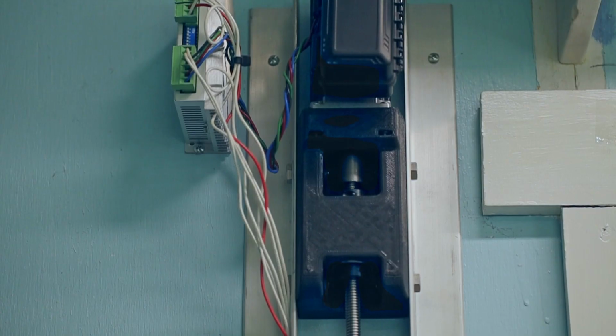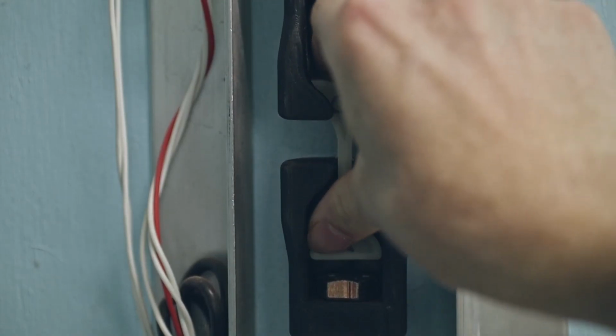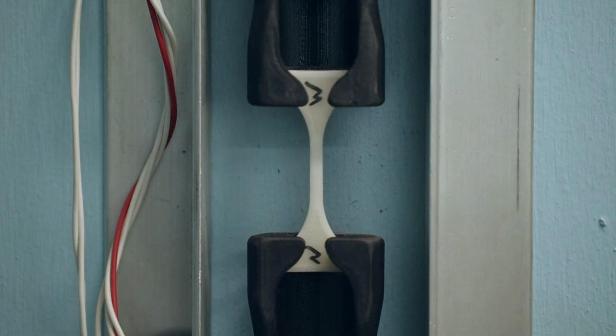Once all the samples were printed and conditioned, ready for testing, I used my homemade tensile tester to test them. That basically involves putting the samples into the jaws of the tester. The tester then pulls the sample very slowly until it breaks, and the profile of force it took to pull that sample is recorded on a graph.